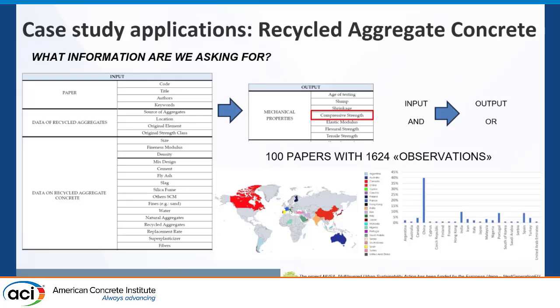So we started interrogating the databases, typically Scopus, and we had to decide what we were asking for. So we ended up with this data on the recycled aggregates. We wanted the source, the location, the original element, and most likely the strength of the parent concrete. This was useful information. Then, obviously, we wanted information about the geometry, the density, and all the possibilities on the mix design of the recycled aggregate concrete. And if you set up this data ontology very precisely, you probably end up greatly diminishing the amount of useful information that you find on the internet.